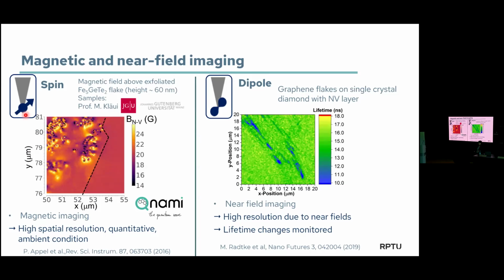As the very first thing we did, well, this is really a quick and dirty experiment. We had some graphene flakes in solution. This is what you can buy from the graphene supermarket or something. And we put it on a diamond where we have the NV centers very close to the surface. In this case, it was 7 nanometers below the surface. We see, okay, at the points where you get a lot of graphene, the lifetime of the NV centers goes down. So we can see there's the points here where the lifetime goes down.